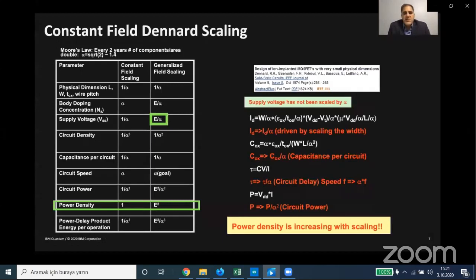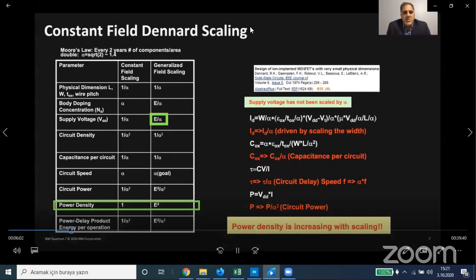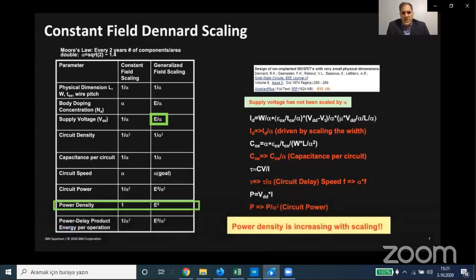In addition to cost, another major challenge is power. Power density, according to Dennard scaling, Bob Dennard, who worked at IBM, developed this prescription for scaling, which is called constant field scaling. If one scales all the critical dimensions by alpha, where alpha is the square root of 2 or 1.4, power density stays fixed. Unfortunately, that has not been occurring in practical terms. We have not been able to scale the supply voltage by 1 over alpha, but rather by 1 over sqrt(alpha), and that's because the threshold voltage is not scaling as prescribed by alpha. Because of this, power density is actually increasing with scaling.